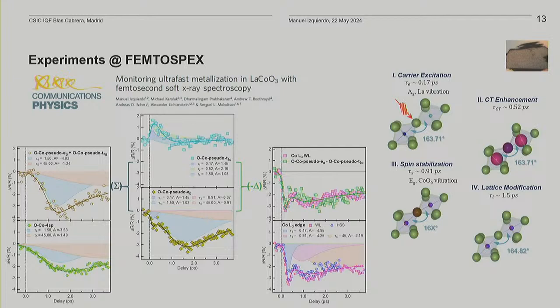What we also found was something very interesting: if you just take combinations of these two delay scans, if you make the sum, you end up with this delay scan that is very similar to what happens at the cobalt 4sp band. And if you make the difference, you end up with this green one that is very similar to what happens at the cobalt L-edge. And so our understanding is that by understanding what happens to the T2G and EG orbitals, you should be able to disentangle what is going on with your system.